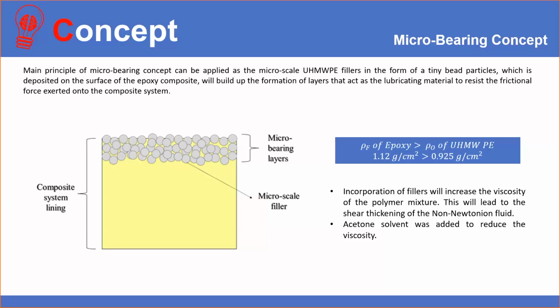So in plastic materials, the incorporation of a short filler will increase the viscosity of the polymer mixture. This will lead to dilatant behavior, which is the shear thickening of the non-Newtonian fluid upon increases in the shear rate, which was first described by Einstein's equations. So due to that, the need of a diluent is important in this study to lower the viscosity of the epoxy resin so that the ultra-high molecular weight PE particles are able to move upward within the working time range.